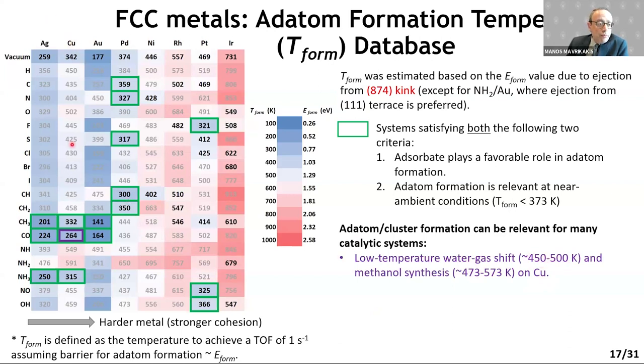Catalyzed by copper, it takes place at around 500 degrees Kelvin. If you now look at copper and CO, this tells me that already below room temperature, at 264 Kelvin, and at the dilute limit, not much CO, I can have one ejection of a copper atom per second. Imagine now this realistic temperature taking place in the factory, how many more ejection events you are going to have.